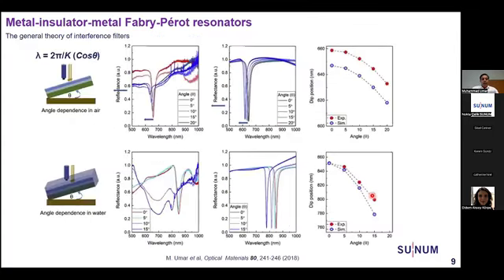Then we characterized it at different angles of incident light. If we change the angle of incident light, the resonance spectrum shifts to a lower wavelength, both in air and in water. We also simulated the spectrum, and the simulated and experimental results are well matched. So this means these devices are also angle dependent.